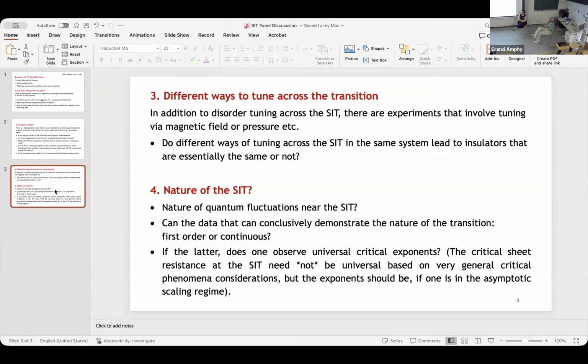That is something we could try. We have seen, for example, not as a controlled experiment, that we put capping layers sometimes, and capping layers actually change the level of vortex pinning. Now, how much it affects the electronic disorder in terms of scattering, we have not checked. It affects the transition, because we discuss proliferation of vortices. But when they hop, they change the properties of the metallic state above them, so it will be more difficult to count.